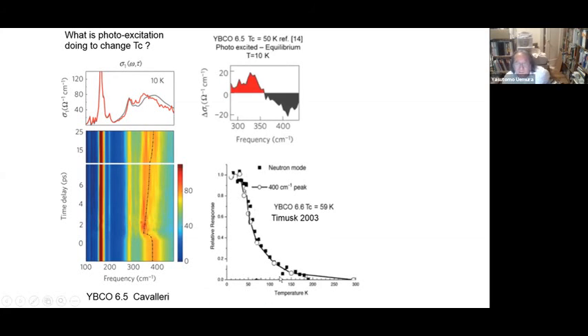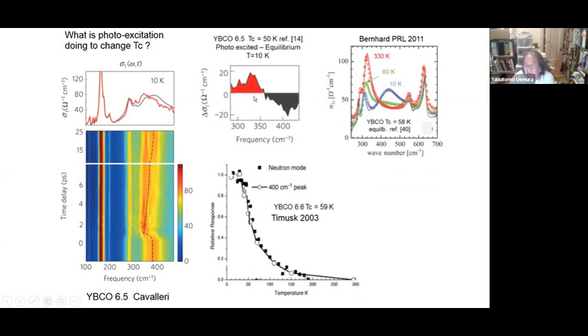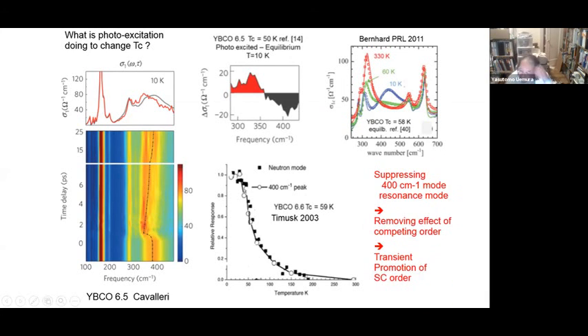So what light does is to put the spectral weight to lower frequency, to this phonon-like mode. And this is more the same as what you would achieve if you have high temperature. This is quite hypothetical, but the light is suppressing the 400 Kaiser mode. And I showed you that the 400 Kaiser mode may be viewed as something representing also the magnetic resonance mode, or the charge-spin soft mode.